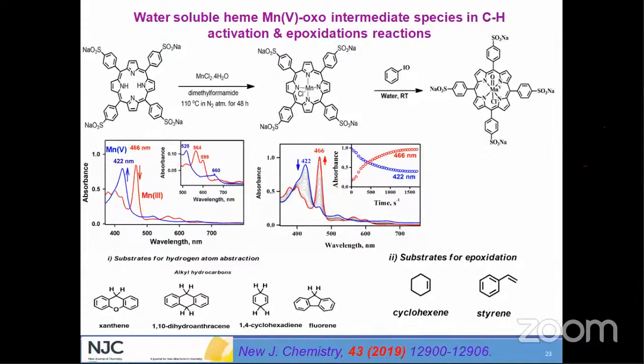So we tested this with triphenylphosphine, and you can see the spectra. The 422 nanometer peak of the manganese 5 oxo species went down on addition of triphenylphosphine, and then the manganese +3 species came back to the original absorbance. Based on that, we also characterized the products formed in the reactions, triphenylphosphine oxide, thioanisole oxide, etc. We got quantitative yields of oxides, and based on that we propose that the species we got is the manganese 5 oxo species.